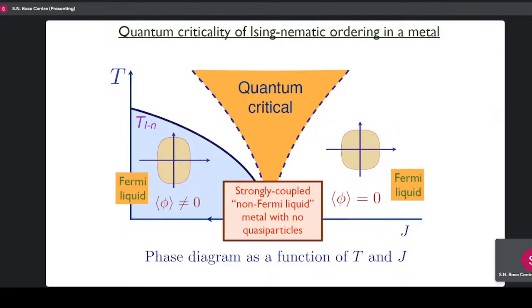But what took some more time to understand, and really was only understood well in the last few years, is this. The one hope would be, okay, let's take this non-Fermi liquid and raise the temperature. Do you get a strange metal? Is this a strange metal for this model? What we've understood only in the last few years, although people were interested all along, and we didn't believe it quite a long time ago, but now it's fully well established, is that the answer is no. It's not. In fact, it's a perfect metal. So we have this strange thing where even though the quasi-particles near the Fermi surface are not well defined, if you did photoemission, it would not look like a Fermi liquid at all. But if you did transport, like resistance or thermal conductivity, it would look just like a Fermi liquid.